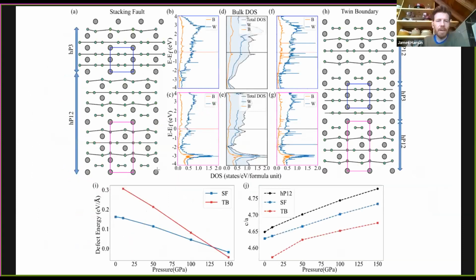I will speak about this very briefly, but what we think is happening is that there are stacking faults and twin boundaries in the material that are MgB2-like, and that disappear at high pressure, which may be a source for the superconductivity that we're seeing. So we're continuing work in the diboride vein. There are a lot of possibilities for different things to do there, and attempting to stabilize the metastable high pressure superconducting phase at ambient pressure. So there'll be more to come on that in the near future.